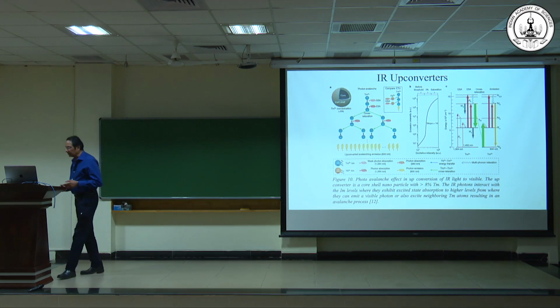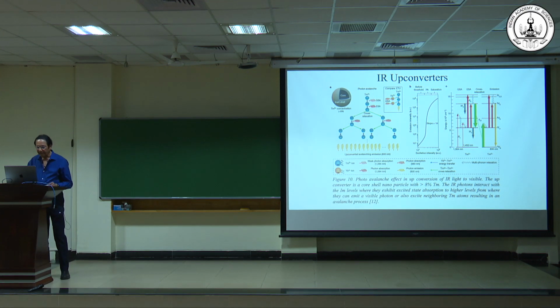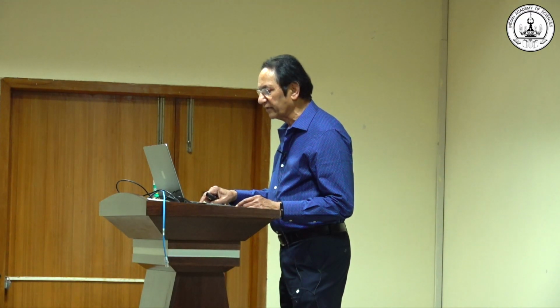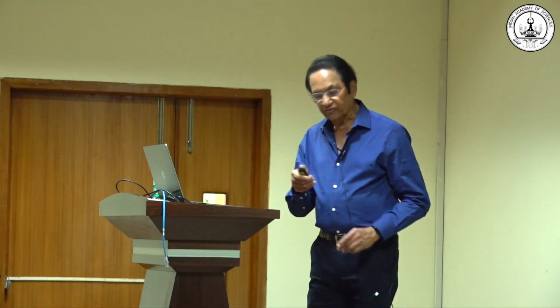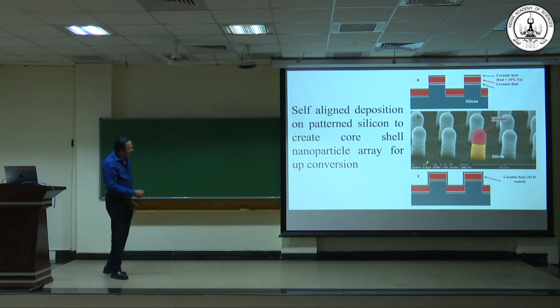And this is where I've come up with a very cool idea, and the idea is like this. We take nanopillars of silicon, right? These are silicon nanopillars, and then on top of these nanopillars, we deposit our layers using pulsed laser deposition. In the PLD process, it's a forward directed process. There's no sidewall coating, so all the coated layers sit right on top of the pillars. You can sort of see here. Other stuff goes in the middle, right?